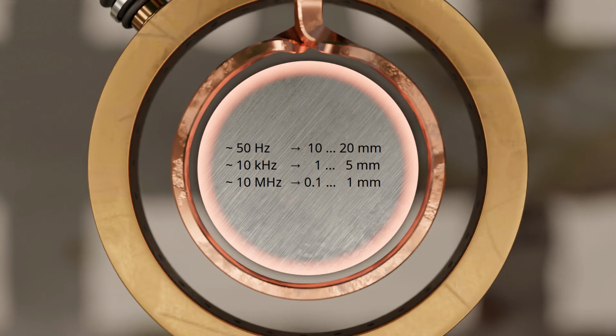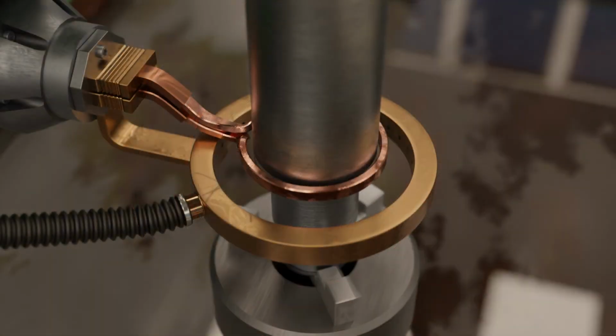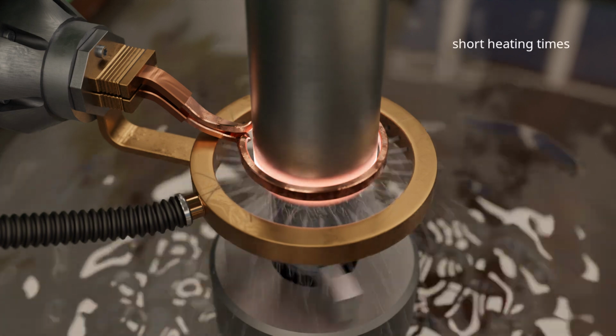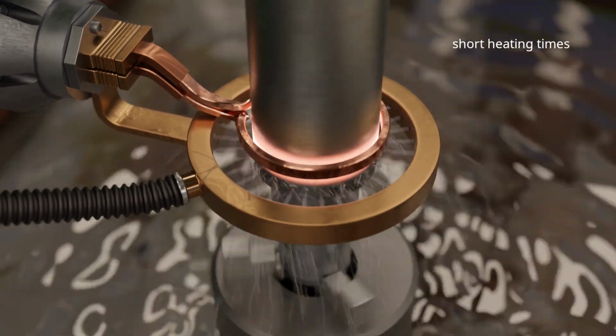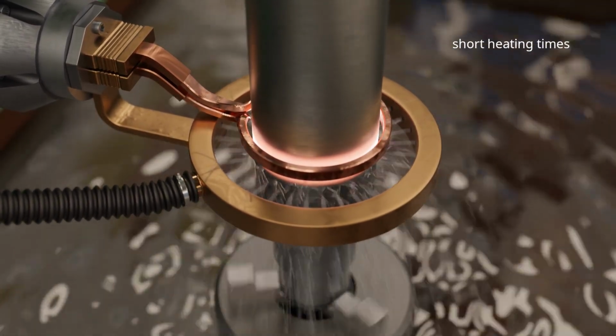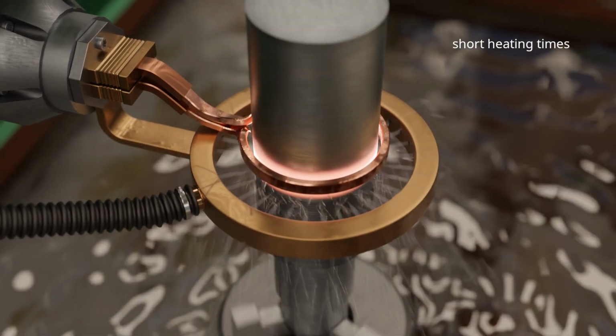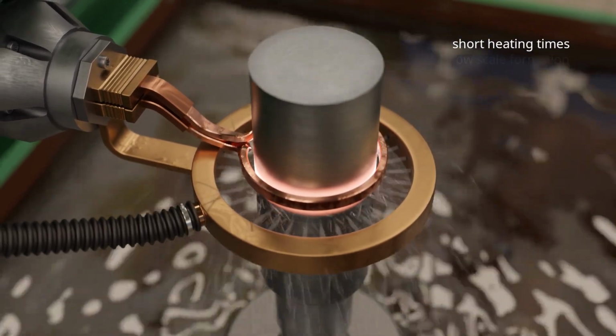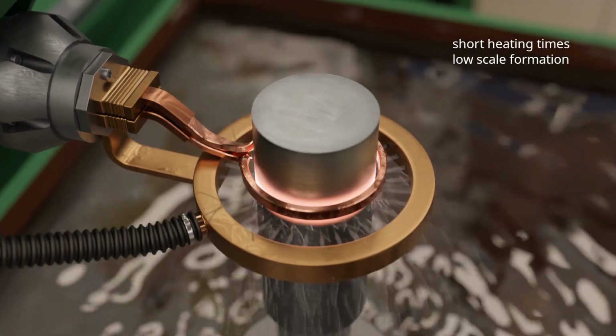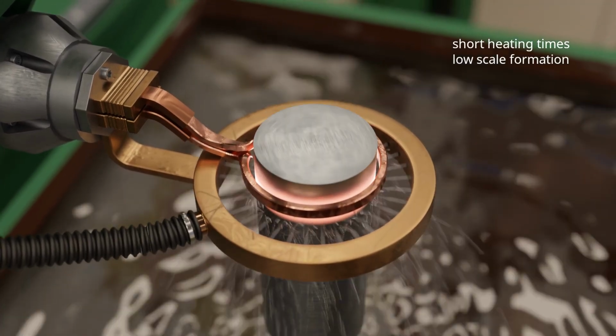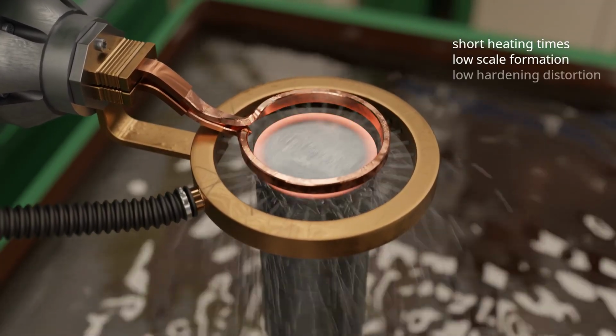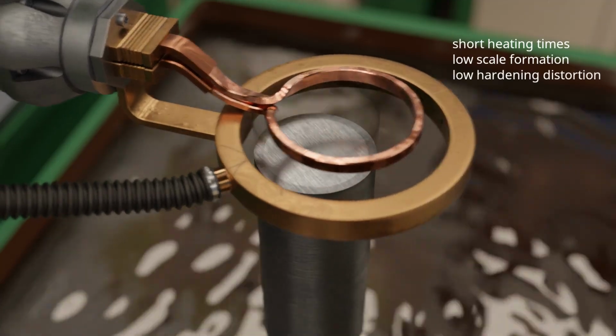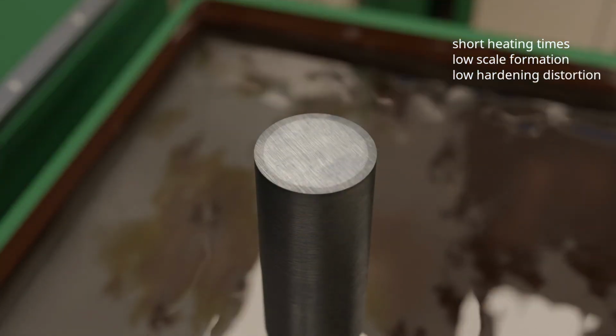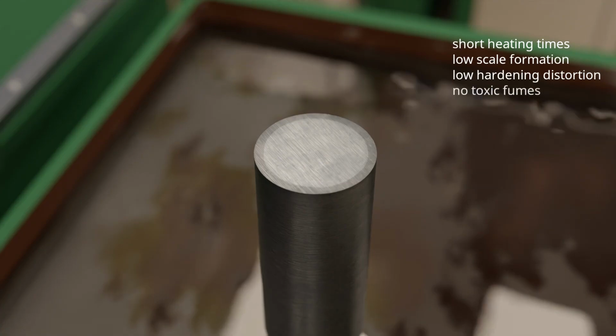millimeter are possible. Heating times for induction hardening are generally much shorter than for flame hardening, as the specific heat output can be around 10 times higher at several kilowatts per square centimeter. This has the advantage that scale formation is relatively low and the amount of post-processing required is reduced. The risk of hardening distortion is also greatly minimized. In addition, induction hardening does not produce any toxic fumes as is the case with flame hardening.